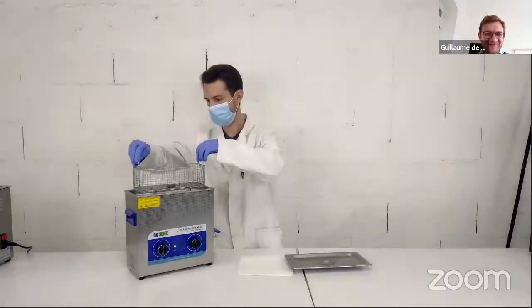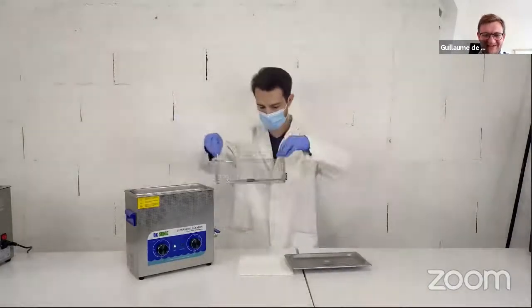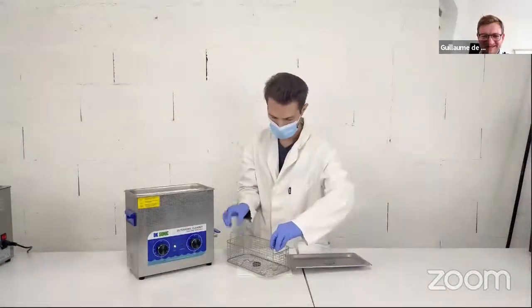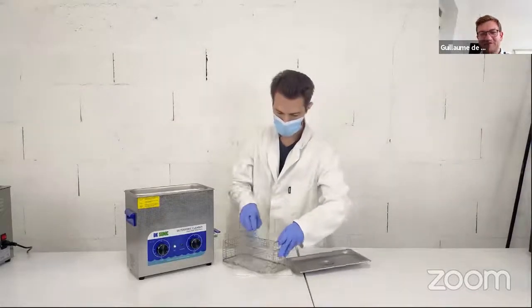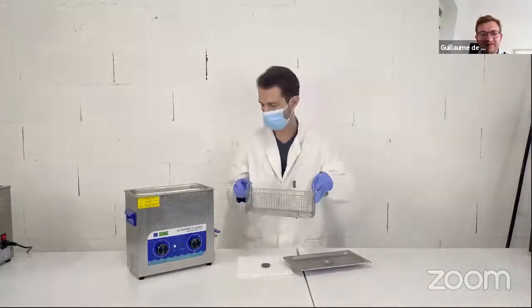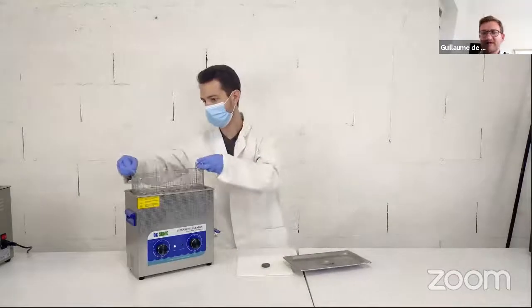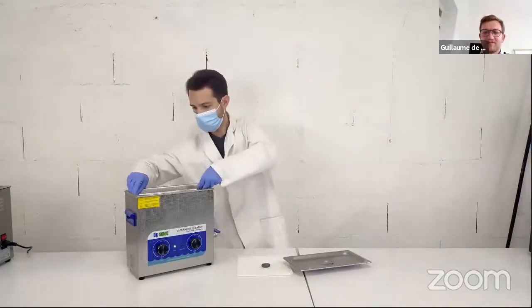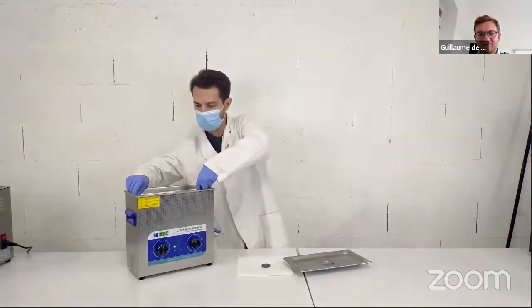A few hours later, you have a nice debinded part, which you just leave to dry for a few minutes. Acetone dries quite quickly. Maximum 1 hour after that, you can usually put it in the furnace.